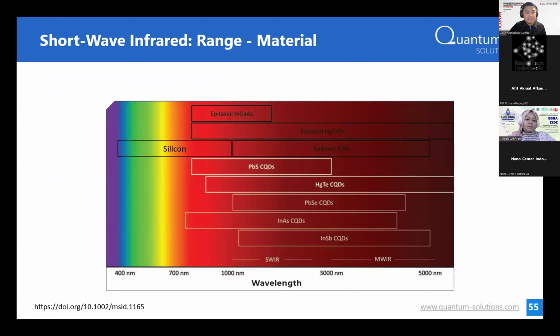Silicon is around here, from the visible until near infrared. And for SWIR application, around here, 1,200 till 2,500, silicon is definitely not working anymore. So you need to work on different materials. I did show you germanium and indium phosphide as well as germanium tin, but with colloidal quantum dots, you can extend this because by changing the sizes, you can also have a different band gap.